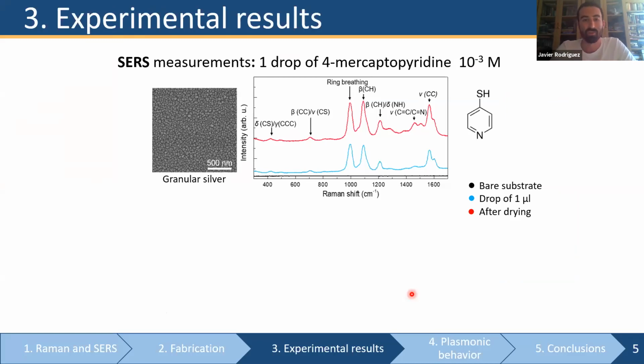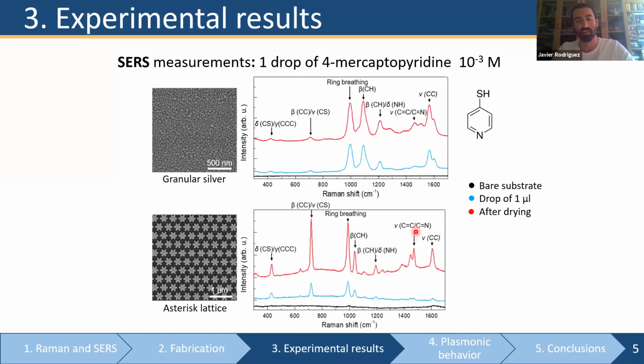So if we compare our structures with a commercially standard substrate for Raman, we can see that this is the performance of a granular silver substrate, where we are just taking a drop of a solution where we have our analyte at a concentration of 10 to the minus 3 molar, and placing it on top of this granular silver and waiting for the drop to dry. Then we perform the Raman spectrum and we get this nice characteristic collection of peaks. But if we repeat this very same experiment, but using one of our substrates, we can see that we get the same collection of peaks, but in general, all the intensity of the peaks is better. And we even get high enhancement of peaks that before were barely visible. So this is good news for the performance of our structures.